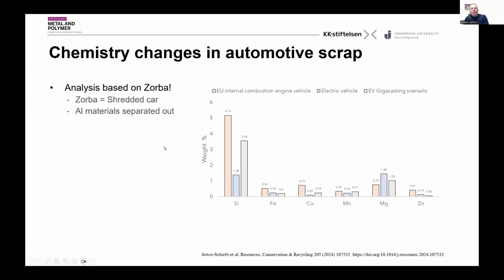If you take the internal combustion, and these are actually based on experimental data where people have shredded cars and then separated them out, for the internal combustion, you can see in the leftmost of these bars you have just above 5% silicon in the Zorba scrap. You can see that you have 0.5% of iron, 0.7% copper, 0.3% manganese, 0.75% magnesium, and 0.41% zinc in the scrap that comes out of this shredded material. And this is what you need to work with.